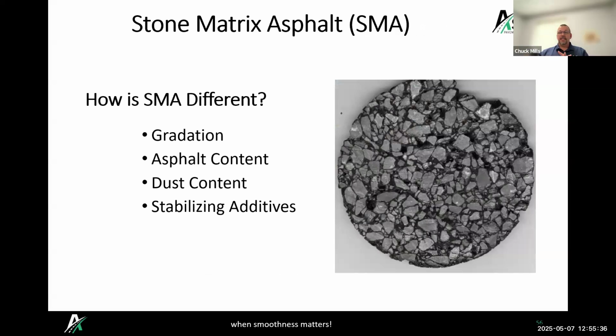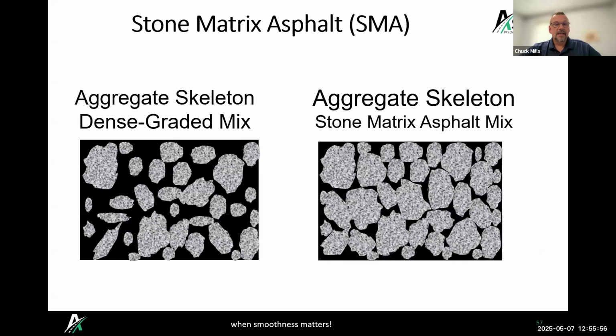Another mix that is different is SMA, or stone matrix asphalt. Really, SMA consists of two parts. It's a coarse aggregate gradation and a binder rich mortar. So how are they different? The gradation, the asphalt content, dust content is all different in a stone matrix asphalt. So you can tell here on the one side is the aggregate skeleton for a dense graded mix versus the stone matrix. You can see with the stone matrix, the key is stone on stone contact.